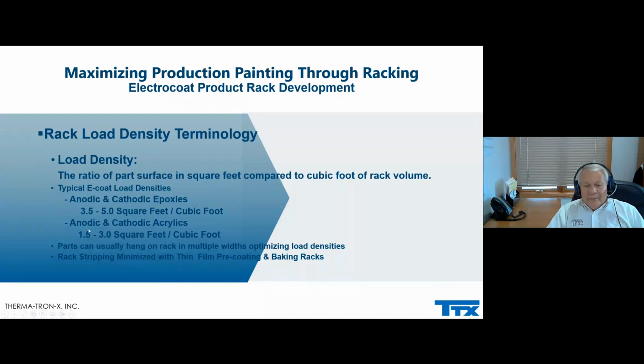In anodics, with acrylics, they have less throw power capability, so your densities are going to be a lot less. With epoxies, they have higher throw power. Parts can usually be hung in a rack in multiple widths, optimizing all kinds of load densities. Rack stripping is minimized with thin film pre-coating of racks and baking those racks, and I'll go into that. Some people don't understand that, but if you get a new rack or have a rack stripped, if you thin coat to about 2 to 3 microns,